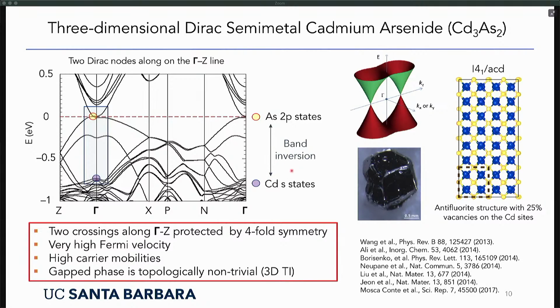And via the bulk boundary correspondence, and I'll talk about this in just a second, that dictates that we have a topological insulator state with topological surface states. Okay, so the gapped phase, so even if we would open a gap here, is a topologically non-trivial phase. And this is also very nicely described in this original 2013 paper.